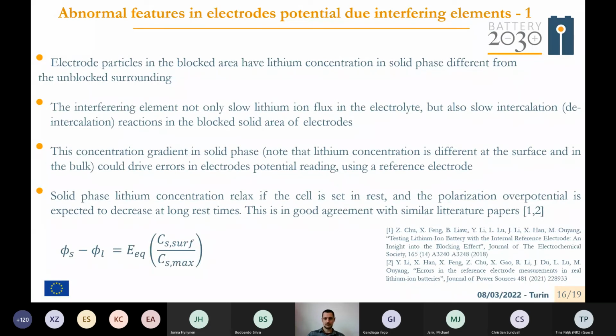We can make another step in this consideration, taking into account that the potential you can read using a reference electrode depends basically on the concentration of lithium in the solid phase. So if the solid phase lithium concentration relaxes when the cell is set to rest, the polarization overpotential you can observe if you introduce a reference electrode in the cell could decrease, and is expected to decrease at longer time. This overpotential is driven by the abnormal distribution of lithium in solid phase and the discrepancies between the concentration of lithium at surface and in the bulk, which are induced by the interfering elements.